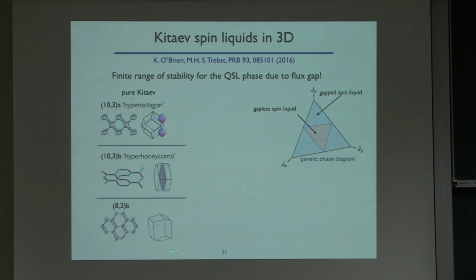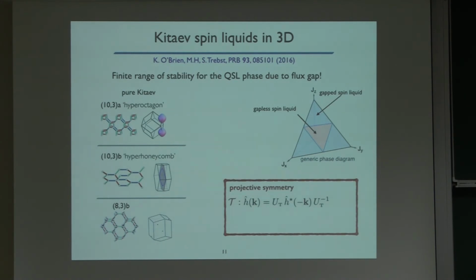So what actually sets what kind of physics you get? Well, in general, we would say, okay, what constrains the physics should be the symmetries. And that is true here as well, but with a slight twist. So we started with a spin system. So the physical symmetries act on the spins. So this is the physical symmetries, but that is not the symmetry that is relevant. What is relevant is how the symmetries act on the Majoranas. And when you do that, you have this gauge field floating around. And the gauge field tells you that symmetries can be implemented in different ways.